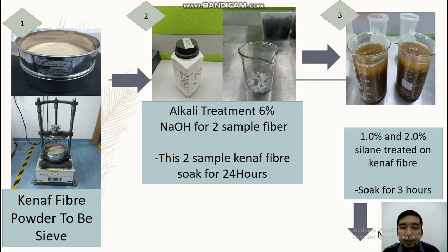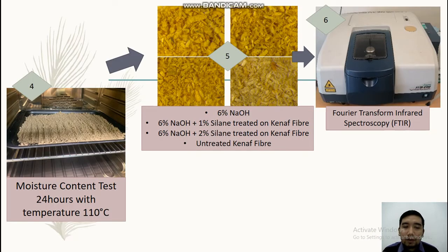Okay, the experiment method is, firstly, I sieve the Kenaf fiber using the sieve shaker at FKM. The second step is alkali treatment with 6% NaOH for 2 samples of fiber. These 2 samples of Kenaf fiber are soaked for 24 hours. After alkali treatment, the fiber goes into the oven for 24 hours for moisture content, and after that the 2 samples are treated with 1% and 2% silane, and this fiber is soaked for 3 hours. After soaking for 3 hours, the fiber is put into the oven for the moisture content test for 24 hours